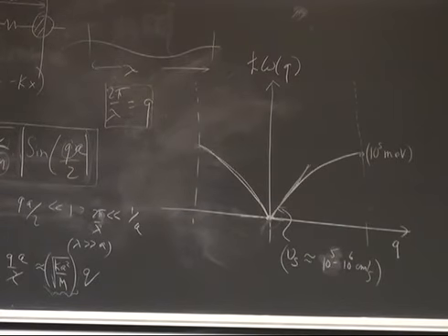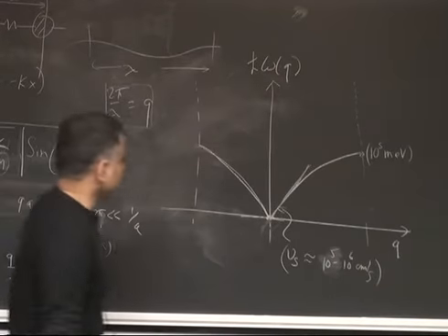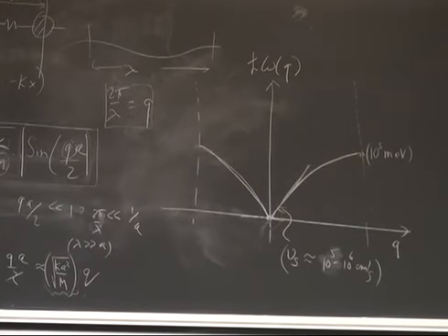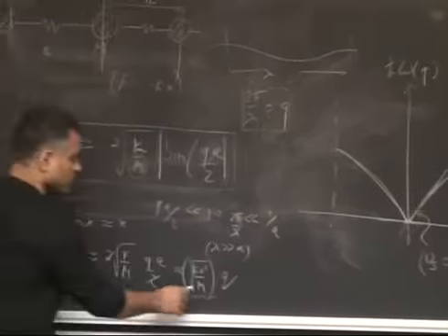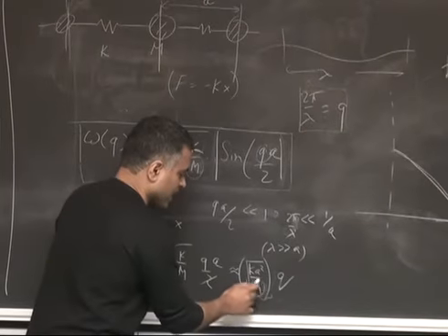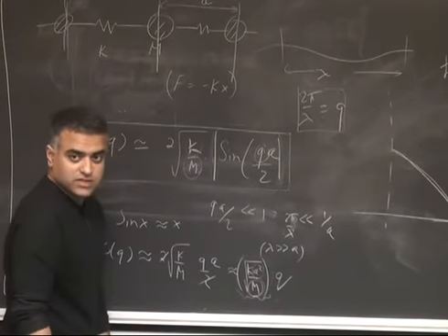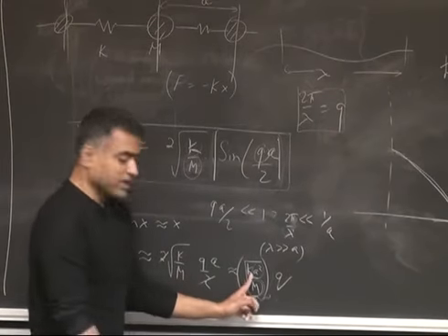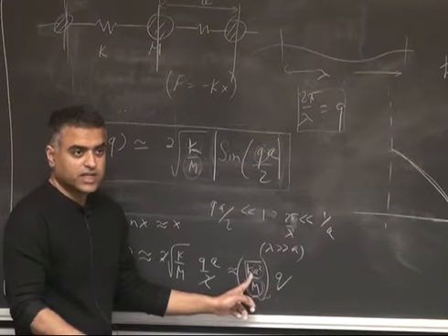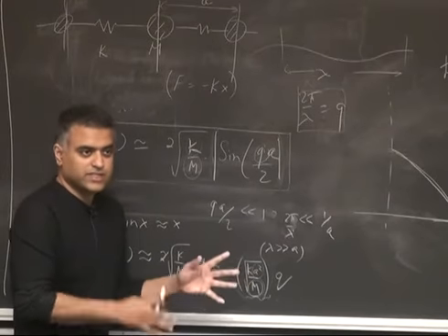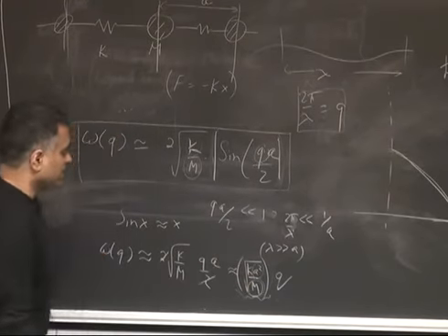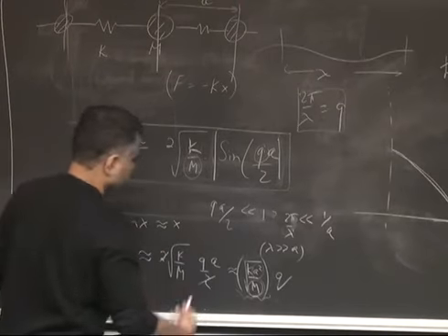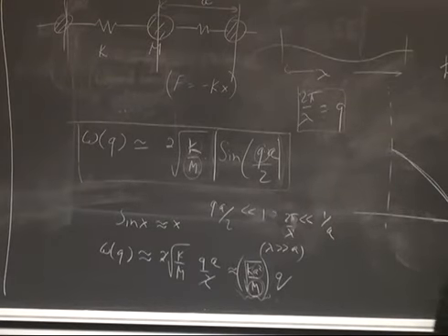Okay, so that's the simple picture. Is that clear? From here you can also, for example, take the mass of the atoms and the lattice constants from spectroscopic X-ray measurements, and if you measure sound velocity, you can effectively get what k is. So there are many other things you can use it for. And you can also calculate k from atomistic pictures and springs and all that.